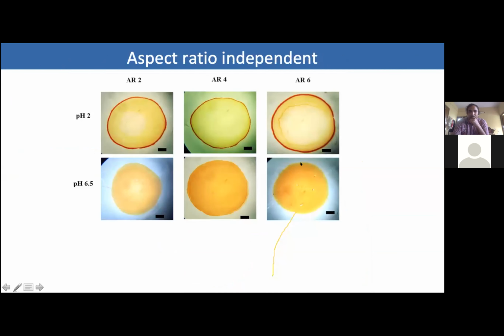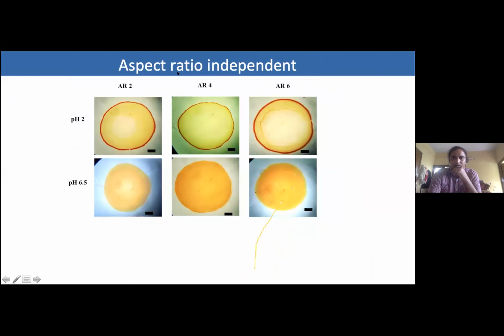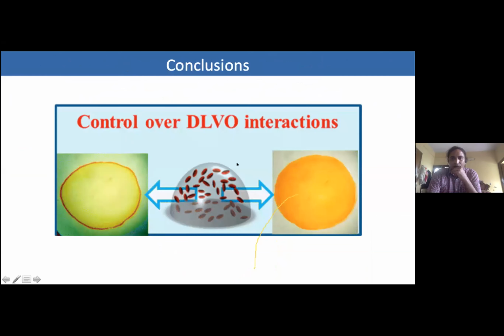Okay, so with this work, I would like to conclude that we get coffee ring deposits at the conditions where the particles are highly charged, irrespective of the aspect ratio, and when the particles are weakly charged, the particle-substrate attraction leads to uniform deposition of particles, again irrespective of the aspect ratio that we have looked at. So therefore, the DLVO interactions control whether there's a uniform deposition of particles or the formation of a coffee ring.